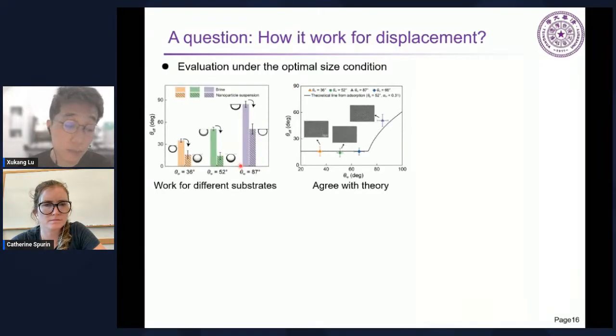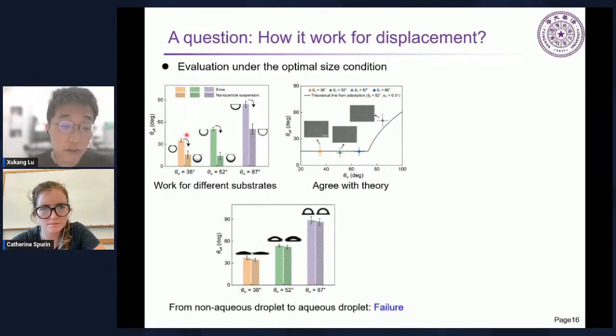And we first change the substrate wettability, which is common in applications and also in our following microfluidic experiments. So you can see the strong wettability alteration can be observed under all different conditions, and it agrees well with theory. But when we change another thing, the whole game seems to change. That is the phase configuration. Previously, we just considered a non-aqueous droplet deposited onto a substrate immersed in the aqueous environment, so that particles will first adsorb onto it uniformly, and then we have the wettability change. But if we flip the process, you can see we have this failure. Nanoparticles play a negligible role in wettability alteration, just within the error bar.